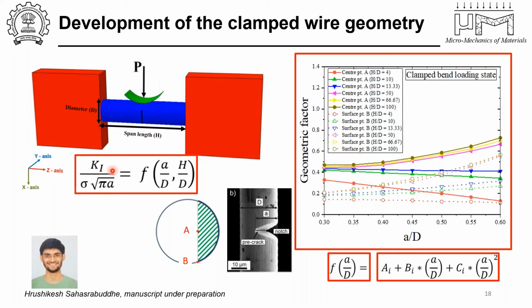Yeah, so again, we came up with solutions for the normalized stress intensity factor or the geometric factor as a function of the A by D, but as well as a function of the H by D. Again, what I want to highlight here is that the aspect ratio keeps coming up as another variable which people have tended to ignore for a long time. They have always written geometric factors as a function of relative crack depth alone. But we have seen that for these kinds of asymmetric notches, the aspect ratio of the beam also plays a very important role. So one can, of course, fit it into equations. And as you can see, again, for small aspect ratios, there is a good chance that the material shows stable crack growth. Whereas for the longer ones, you don't see that kind of stability for longer cracks.